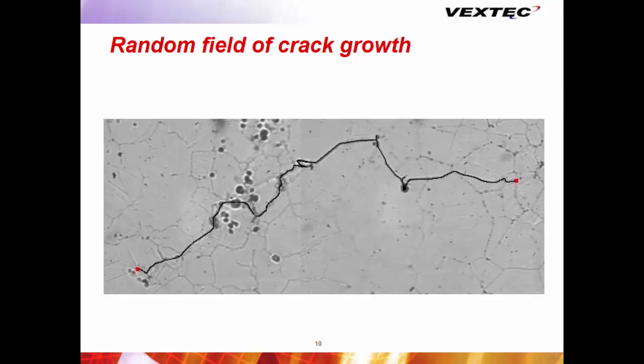And then here's another example, kind of from that first one. So here's a crack as it starts to get long, but it still recognizes that the microstructure is there. As a matter of fact, the microstructure is going to drive the crack growth until the process zone, until the plastic zone is so big that it can average out all those microstructural inhomogeneities. But at very low loads, it might always be microstructurally driven. The important thing is not so much that it has this tortuous crack path, but that the tortuous crack path drives the rate. So two of these cracks can have a much different number of cycles to get to a certain small size because of tortuosity. One could take one path, the other takes another path, and as you know, driving around Detroit here, the path you take determines when you're going to get there, and that's true for these cracks also.